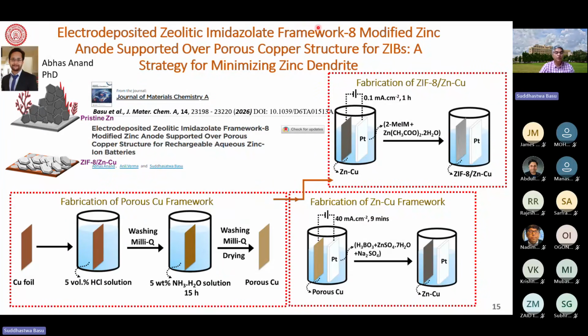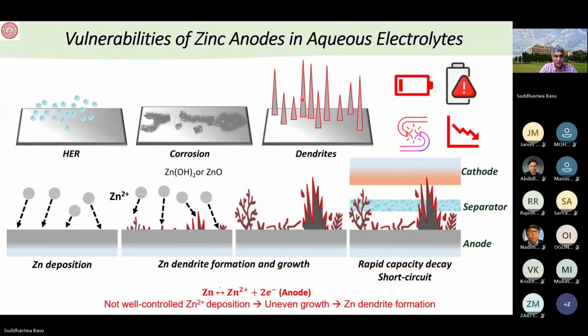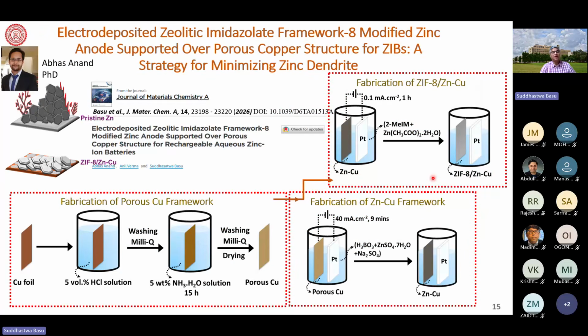So what we do, we have decided to have a zeolitic imidazolate framework, or ZIF8 framework, on a zinc electrode, which is being used as an anode electrode in the zinc aqueous battery. And we feel that this will prohibit the growth of dendrite that we have shown you here, which reaches the cathode and causes shorting in the case of the zinc aqueous battery. We feel that it would do that.